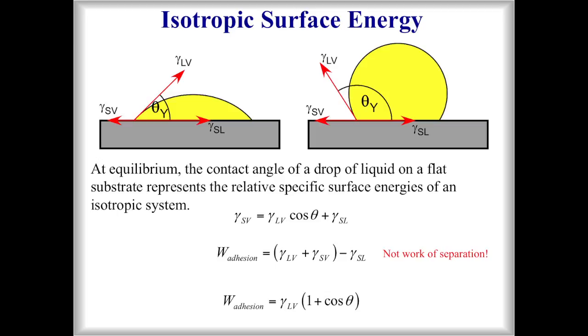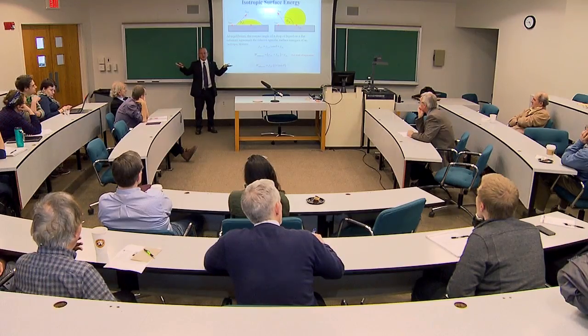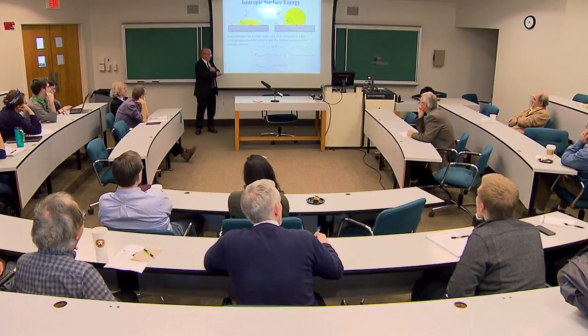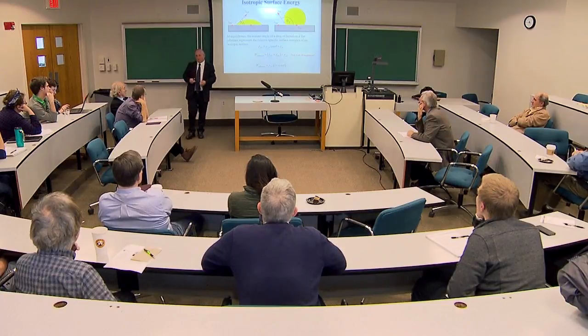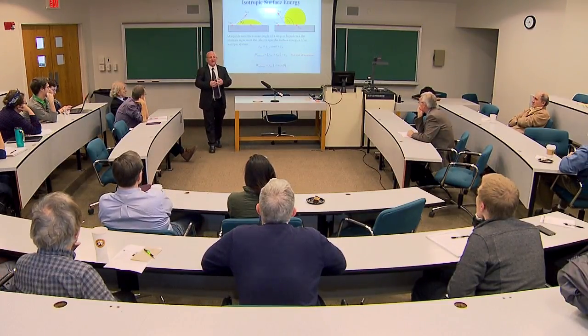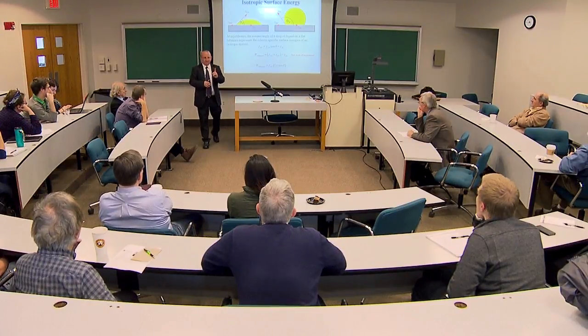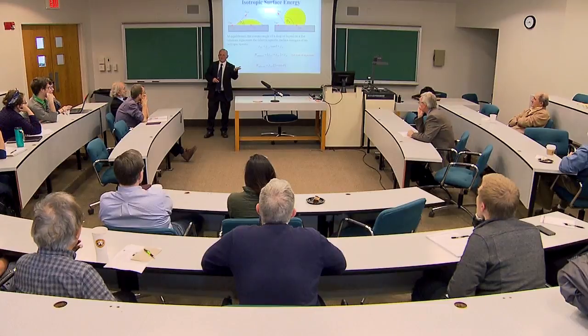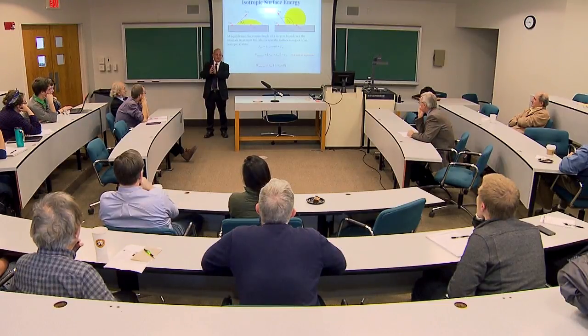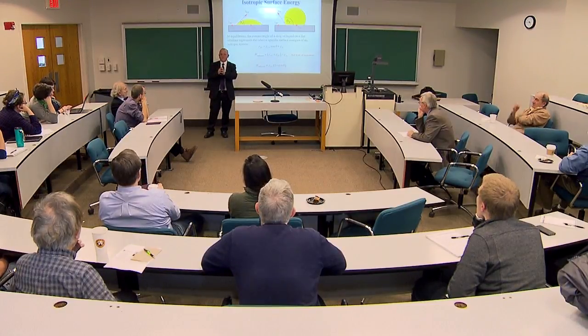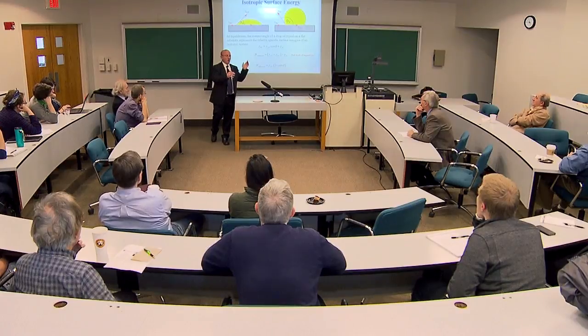In addition to Young's equation, we have this equation of the thermodynamic work of adhesion, which is from a guy named Dupre. And it's basically saying that we're going to look at the surface energy of the liquid and the surface energy of the solid, and now we're going to bring them together and make an interface, which is here, and this energy difference is the gain or the payment that we have to make in order to generate that interface. Okay? Please be careful. This is the surface energy of the solid at equilibrium, the surface energy of the liquid at equilibrium, and the interface afterwards at equilibrium. That's not what we measure if we were to ideally, without some plastic deformation process, separate this droplet from the solid.